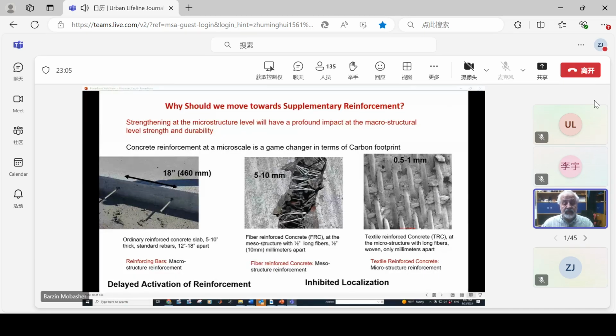Another goal that I want to address is that everything we have done up to now has been from a macroscopic point of view. Look at the electronics industry, how they have gone to the microstructure, how they've used material science. And the question is that we reinforce materials this way, and we expect that about half a meter away, a crack that's forming, a rebar would sense the load that's applied on it and reduce the stress on it by carrying that load. This is not going to happen. This concrete has to fully crack before the rebar even gets activated and carries the load. What that means is that we have a fracture problem that we need to solve.